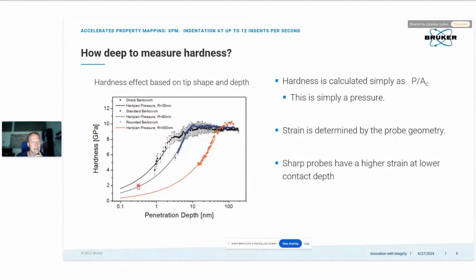And so as you can see, you start measuring the real hardness values at very different stages, or from different penetration depths, if you look at these curves. So you see the increase in the plastic deformation, basically the stress level in your material. At some point you are reaching the yield stress. So this is the plateau for your hardness values. If you want to reach very high resolution on your hardness map, it's also beneficial to have a very sharp probe, because then you can produce small indents, produce the high stresses right from the beginning, and then you can pack the indents close to each other and reach the high resolution in your hardness map.